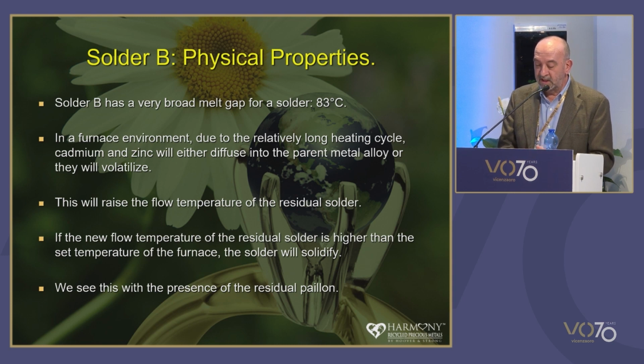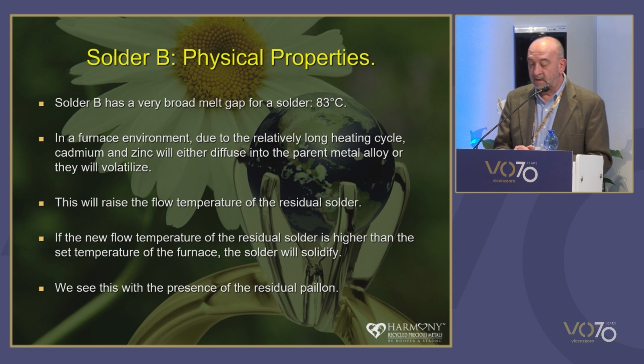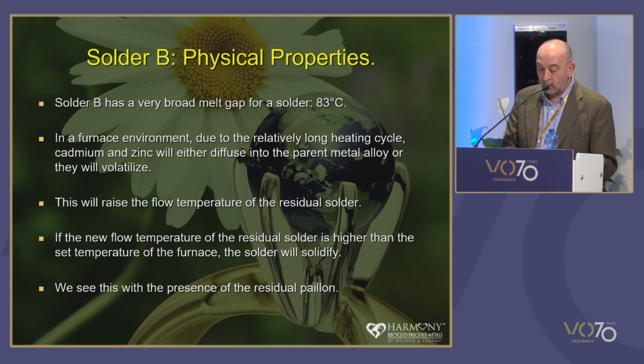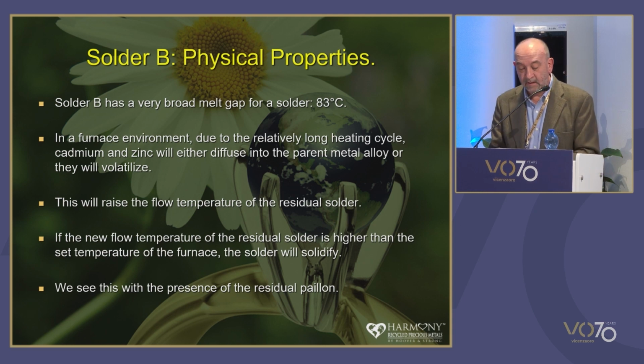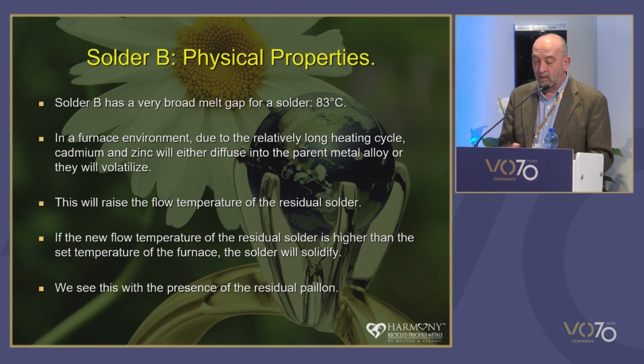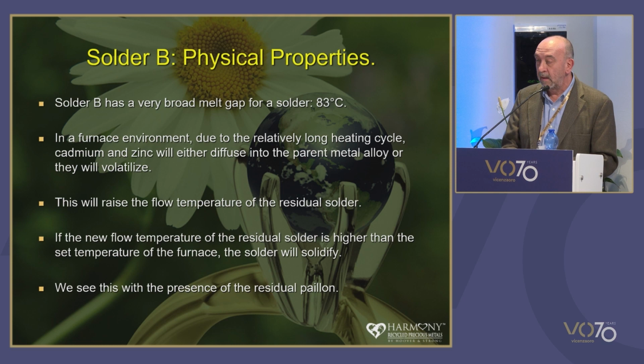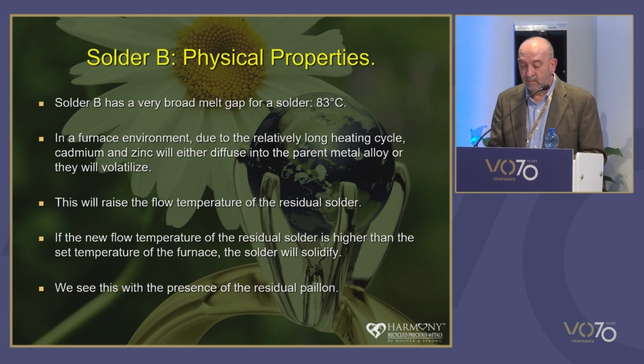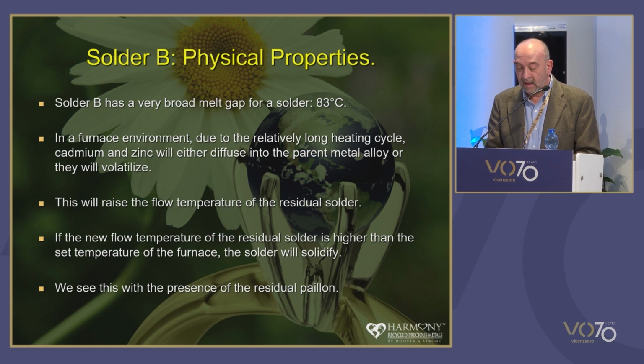So both cadmium and zinc are included in this solder alloy to lower the melt temperature. In this case, the potential is there for either one or both to diffuse into the parent metal or just to volatilize off and change the composition of the solder that you've got left. Either mechanism will result in compositional change over a period of time in the furnace and will result in an increased melt and flow temperature for whatever solder is left.